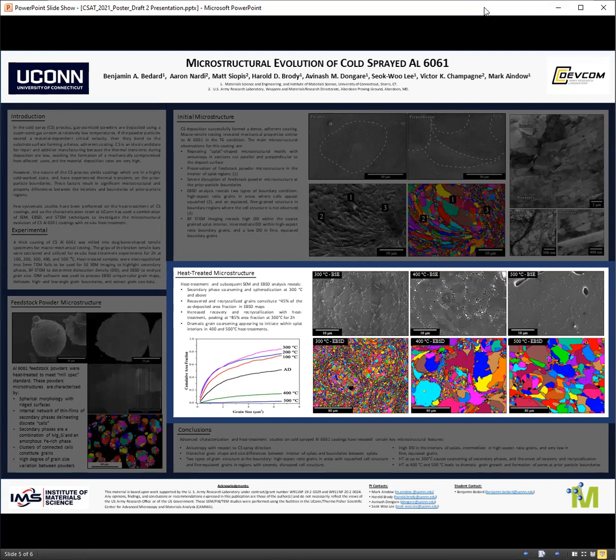Secondary phases coarsen at and beyond 300 degrees Celsius, with some degree of solutionization appearing to occur at 500 degrees Celsius. Grains appear to undergo recovery and recrystallization up to 300 degrees Celsius before dramatically coarsening at 400 and 500 degrees Celsius. Cumulative area fractions extracted from EBSD grain maps reveal that the initial coating microstructure is comprised of nearly 45% recrystallized material relative to the initial powder microstructure, and that jumps to about 85% of the area fraction after a 300 degrees Celsius heat treatment.